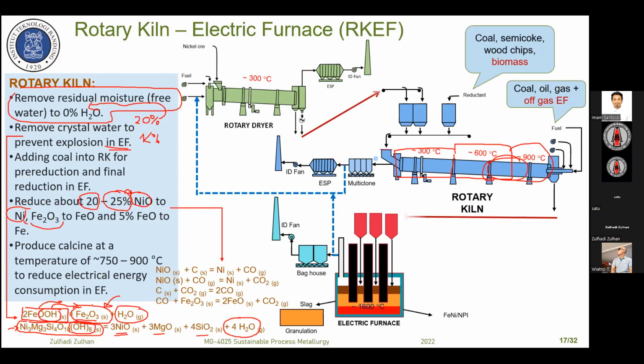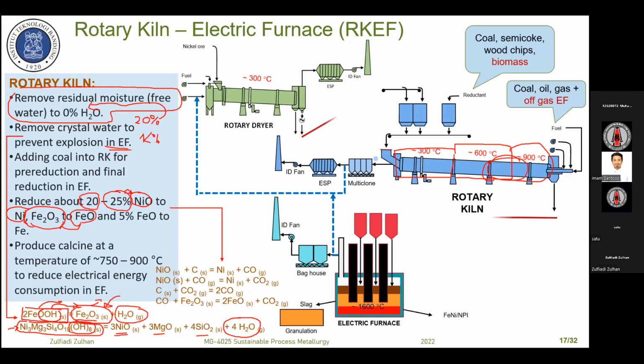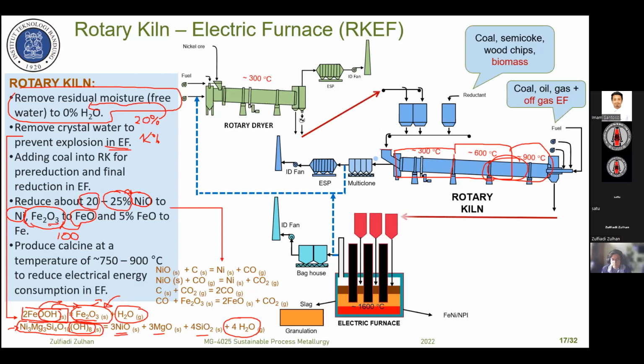And almost all hematite, after we dissociate this kind of mineral, is reduced to iron oxide, to wustite. We can reduce the oxygen here to produce close to 100% wustite. And for sure, from hematite we go first to magnetite, and then the last is to wustite. Around 5% of wustite is reduced to metallic iron.